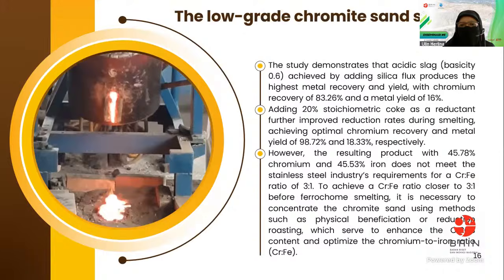So in this preliminary study, the acidic slag achieved by adding silica flux has produced the highest metal recovery at basicity 0.6. The chromium recovery result is 83.26%, and the metal yield is 16%. And then adding 20% stoichiometric coke as a reductant improves the reduction rate. The result is chromium recovery of 98%, and then the metal yield is 18.33%.